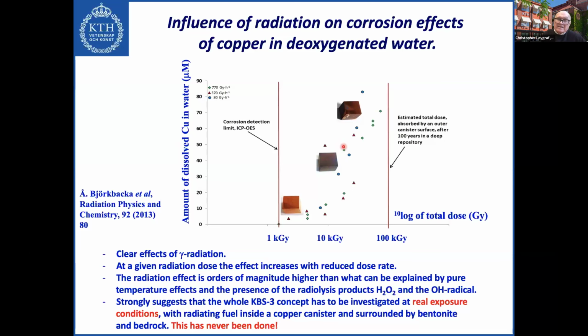The interesting thing here is that the radiation effect on corrosion is orders of magnitude higher than what can be explained by the pure temperature effect of radiation and what can be explained only by the presence of radiolysis products, hydrogen peroxide or the OH radical. And this shows that the whole KBS-3 concept needs to be investigated at real exposure conditions. If we want to consider all these effects together, the effect of radiation in combination with the complex microstructural changes we saw from the exposure to synthetic groundwater, we cannot study each individual phenomenon and its influence by gamma radiation. We have to put everything together, and this has never been done.